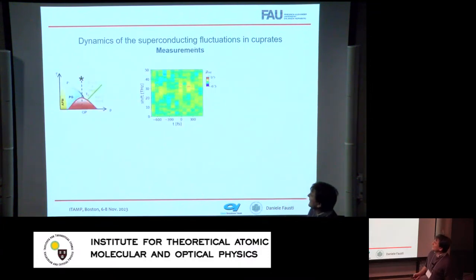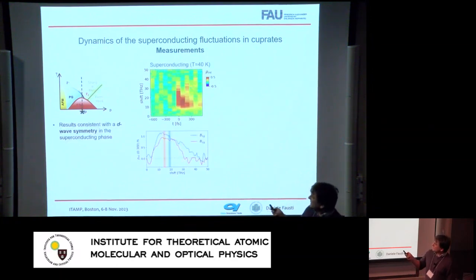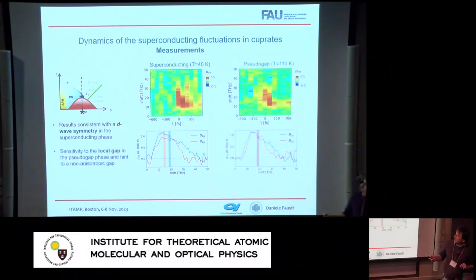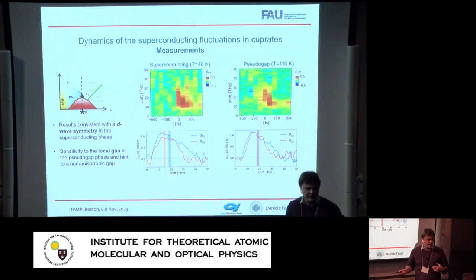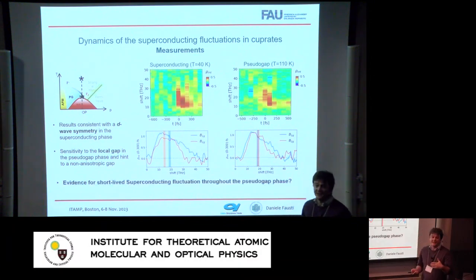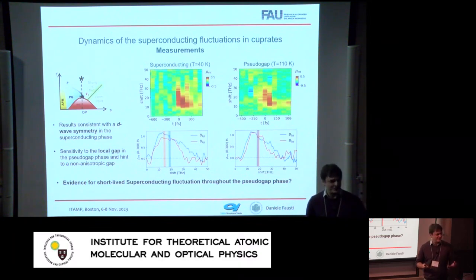But what's more interesting, and here it's not a result yet, but I would like to present it as a discussion argument, to which I hope I manage to get at the end, is that if I go outside of the superconducting state, this scattering feature is completely gone. If I go inside of the superconducting state, it appears. So it is somewhat associated to the superconducting state. But if I go above the critical temperature, I do see that I have a remaining scattering feature, which is similar to the scattering feature I have in the superconducting state. And this is not true for equilibrium Raman spectroscopy. If I do a continuous Raman spectroscopy, this electronic Raman scattering disappears at the critical temperature. That's why historically it was connected to the onset of a superconducting state.